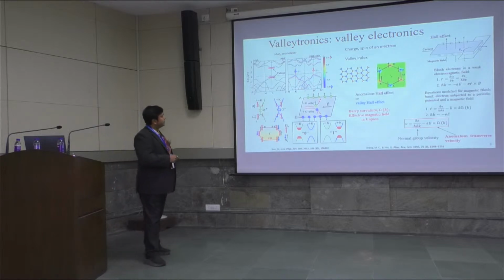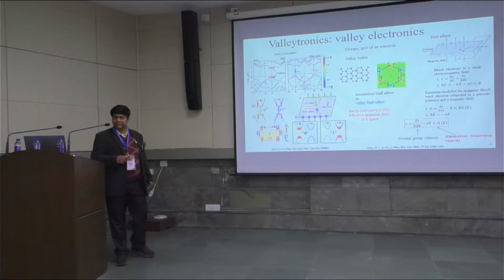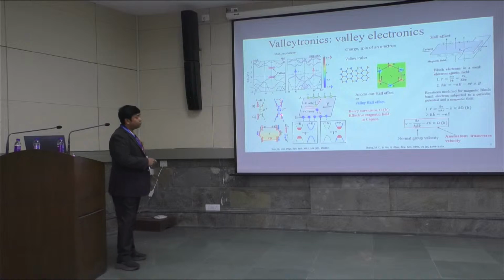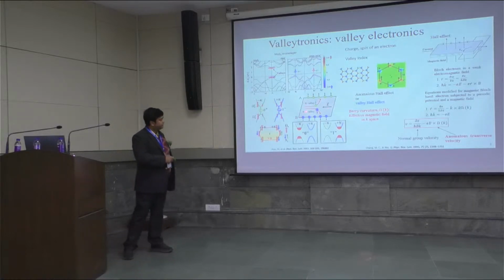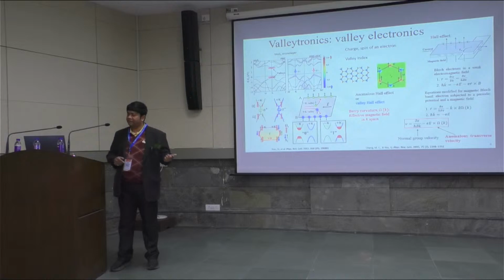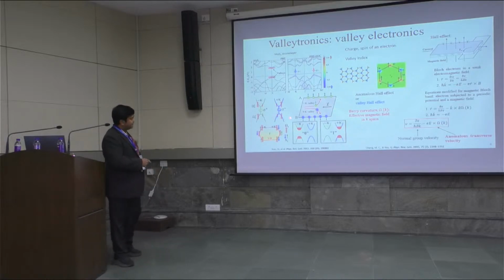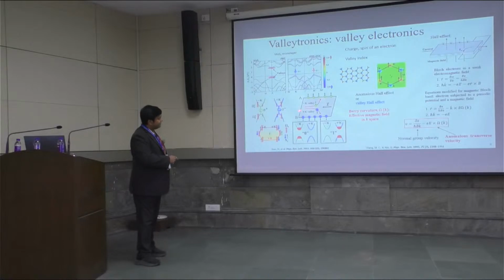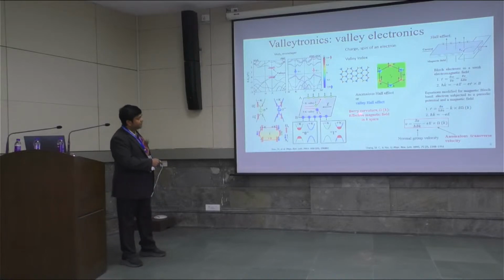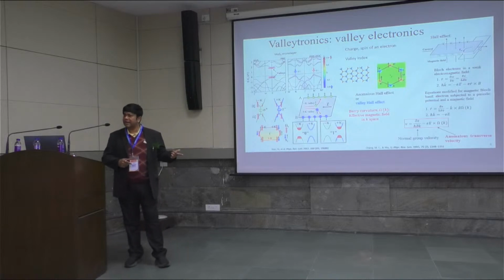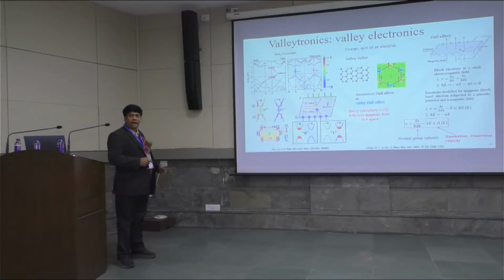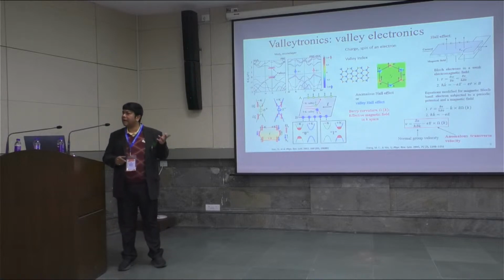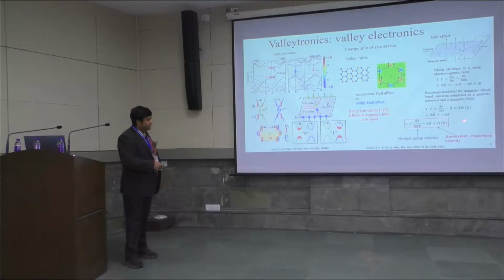So first of all, you would need to generate carriers in these valleys. How would you do that? That is by using light of appropriate polarization. You need left circularly polarized light to populate the plus K valley, and right circularly polarized light to generate carriers in the minus K valley. Then, like in the Hall effect, when you study the Hall effect experimentally, you need to turn on the electric field, and then the carriers in this valley experience an effective magnetic field in K space, which is due to an intrinsic property of the material having broken inversion symmetry and spin orbit coupling. That is the Berry curvature. And the higher the spin orbit coupling, usually the higher the Berry curvature and the higher the valley polarization. So this is a v cross v kind of term here.